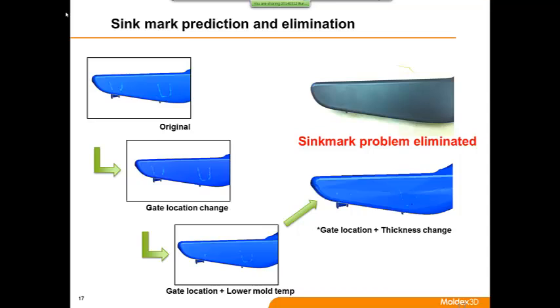And of course, today we won't talk a lot, but we can also expect Moldex3D to improve your sink mark. Originally, you see on the top left corner, two sink mark locations. They are slightly brighter in color. And gate location change might not help much. So you might want to change your mold temperature. When you lower the mold temperature, Moldex3D can capture that slight difference in temperature and get the estimation of the frozen layer correct. Once you lower the mold temperature, the frozen layer is thicker and the sink mark is not so obvious. So we can get rid of this problem.